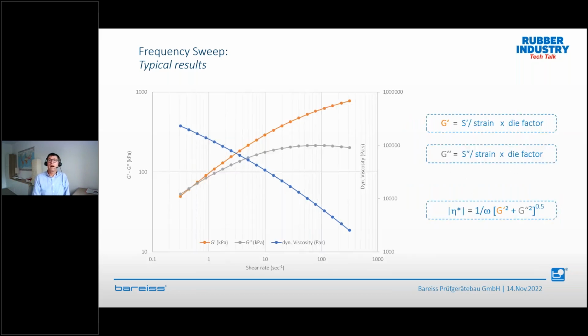So again, how to calculate it? For G prime, you remember, we measure a torque, we divide it by the strain, and we multiply it by the die factor of our cone rheometer. It is the same for G double prime, and also for the dynamic viscosity. So if you have the torque values as a function of strain, you can very easily calculate modulus and dynamic viscosity every time.